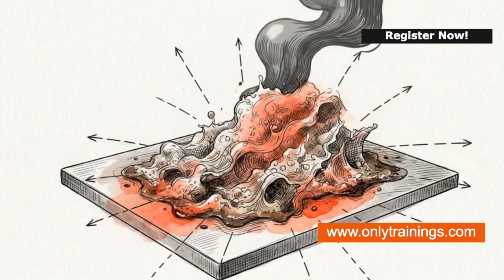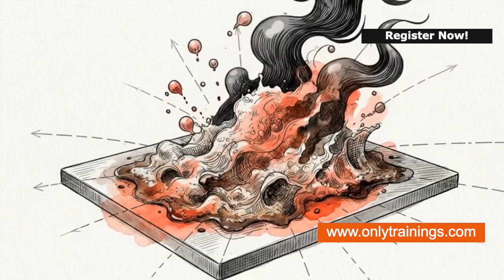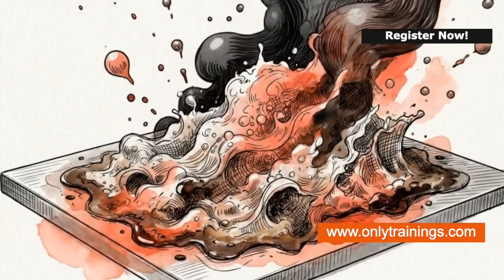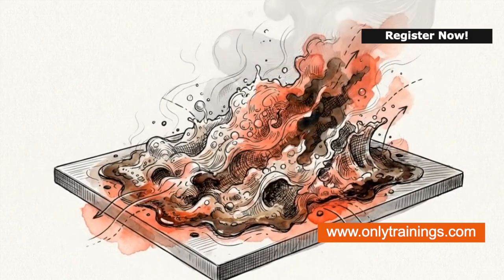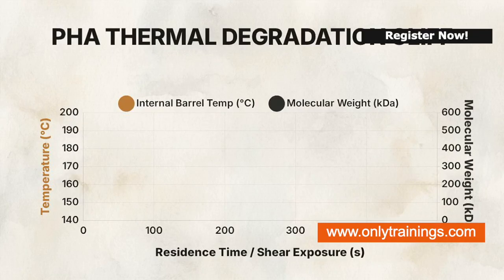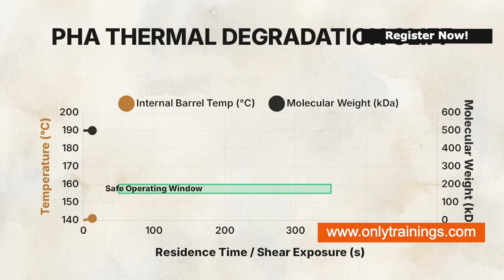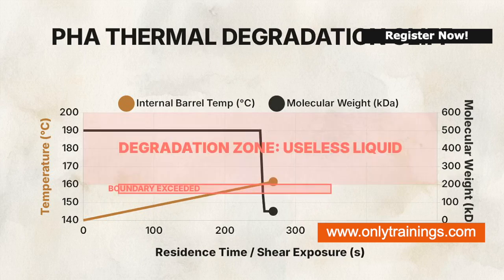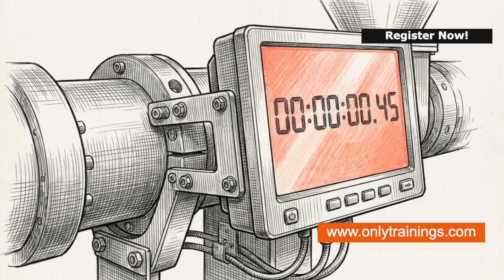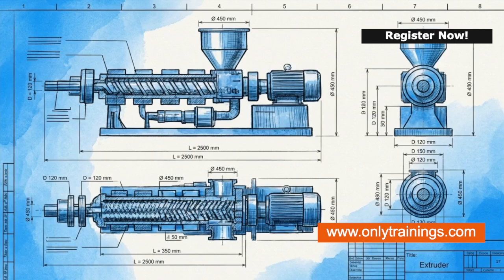While PLA and PBAT are sensitive, polyhydroxyalkanoates, or PHA, and PHBV are highly volatile. Under uncontrolled heat, these organic solids melt down and structurally degrade. Returning to the matrix, we see the operating constraints for PHA. The thermal boundary box is incredibly narrow, allowing almost zero margin for error. The exact moment barrel temperature exceeds this boundary, the polymer experiences catastrophic loss of molecular weight, becoming a useless liquid. Managing this requires strict mechanical control over residence time. The polymer cannot stay inside the heated barrel a second longer than necessary to melt and mix. With PHA formulations, the physical dimensions and capabilities of the extruder dictate whether a chemical formulation can survive the manufacturing process.